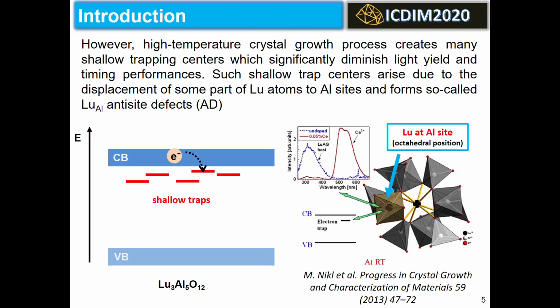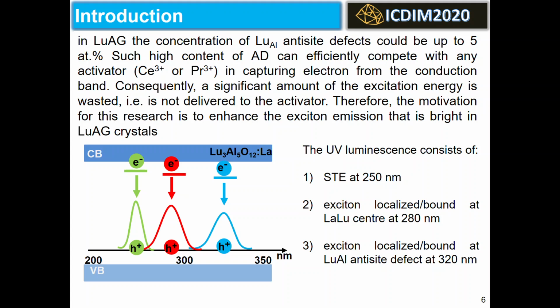and hole trapping centers. As we can see in this figure, the antisite defect emission in undoped LuAG shows strong luminescence with intensity close to the intensity of cerium luminescence in this matrix. This means that antisite defects are very efficient in electron trapping. In LuAG, the concentration of lutetium-aluminum antisite defects could be up to 5 atomic percent. Such high content of antisite defects can efficiently compete with an activator like cerium or praseodymium in capturing electrons from the conduction band. Consequently, a significant amount of the excitation energy is wasted, which means it is not delivered to the activator.